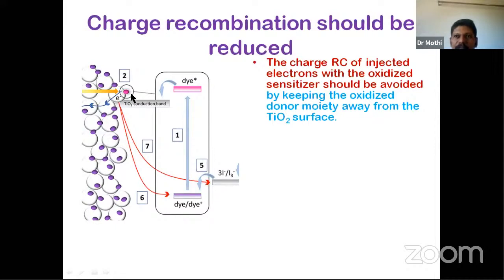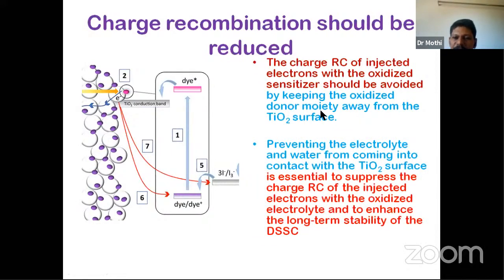So we should do a process by which the oxidized dye is not very close to the TiO2. This is done by increasing the distance between the anchoring group and the dye. For example, if you have a spacer, that can give the required space between the dye and the TiO2, so that only the photoexcited electron injection happens and not the reverse recombination. Similarly, the electrolyte also should not be very close to the TiO2 surface. If the electrolyte is touching the TiO2 surface, then this recombination can happen very easily.